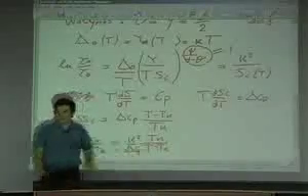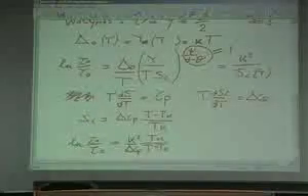What you get then is this expression, but with T here, not Tk. I was a bit sketchy here. The correct expression gives T divided by T minus Tk, which is not exactly Vogel-Fulcher. It will be Vogel-Fulcher when you are very close to Tk. I agree.